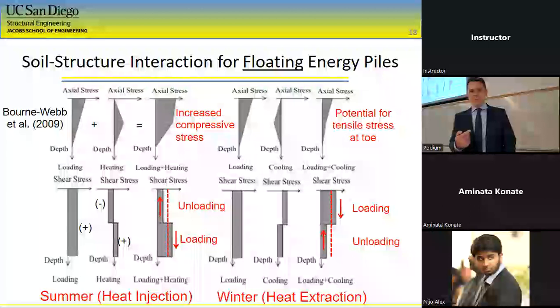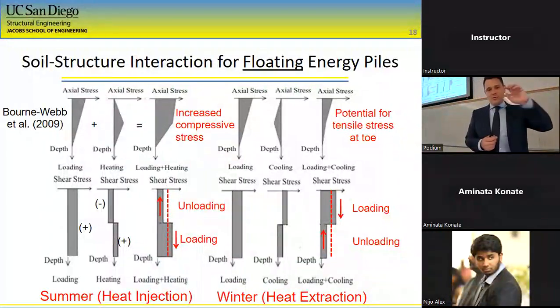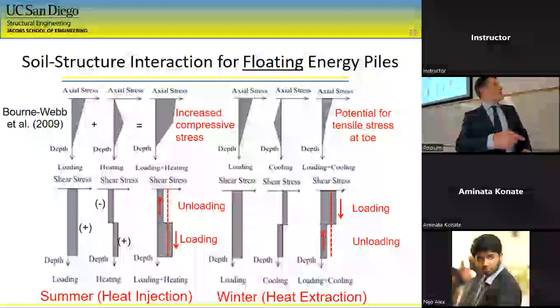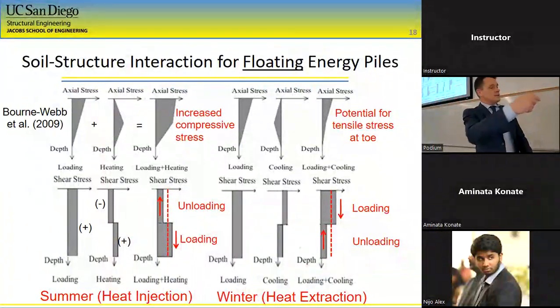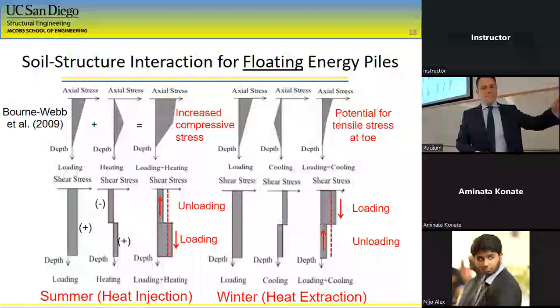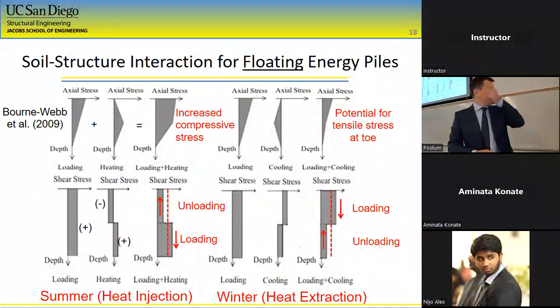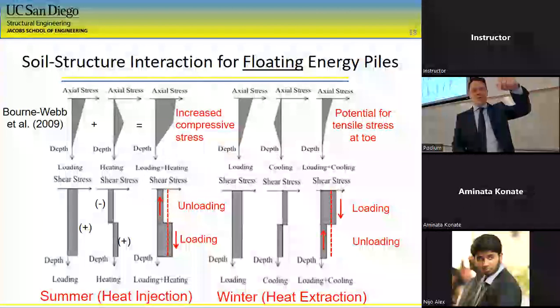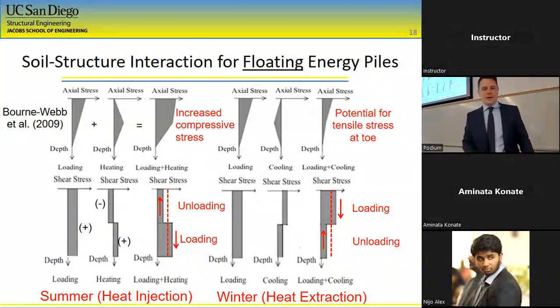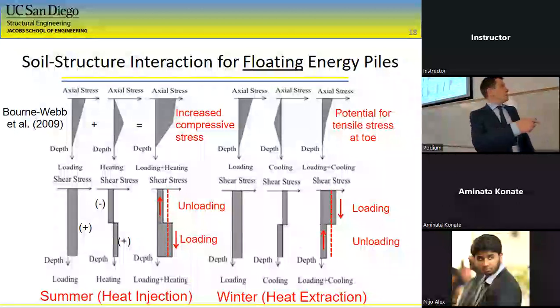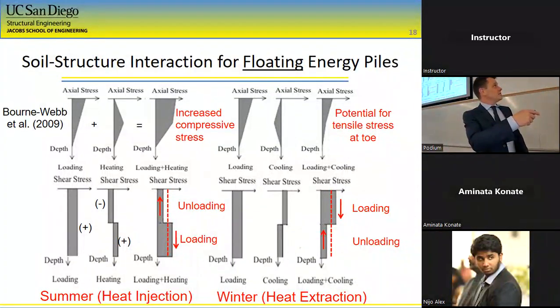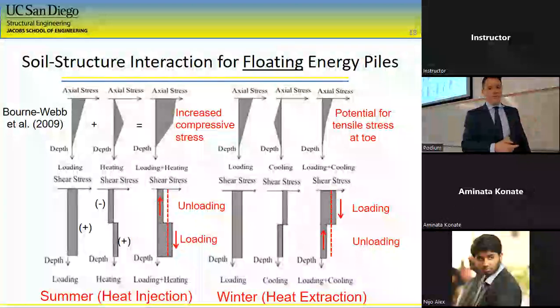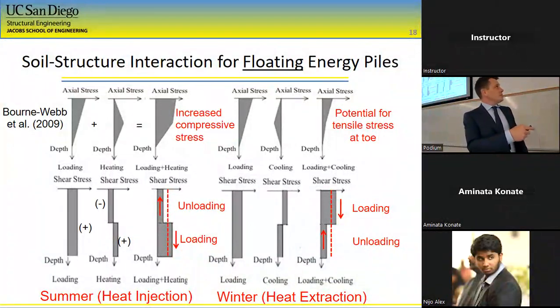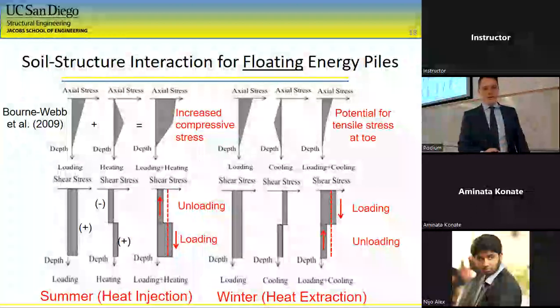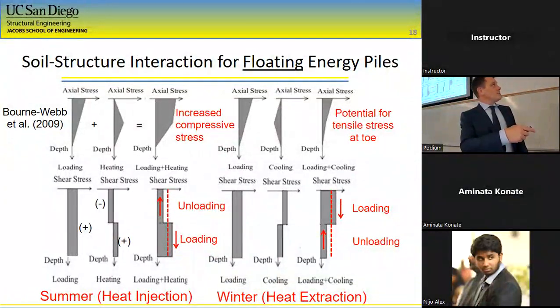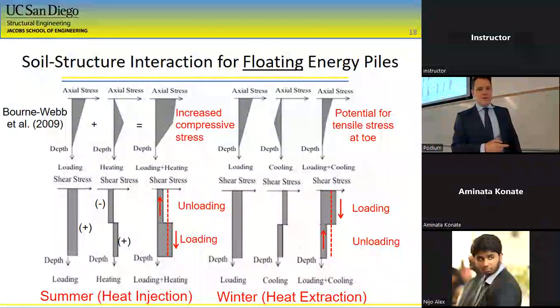So for a very simple case where you have a floating energy pile, this is a pile that has no end bearing. If you apply a load to the top of it, its stresses are going to be distributed somewhat linearly with depth. So at the bottom, there's no stress, and at the top, you're having a stress equivalent to the applied building stress. And then you're going to superimpose on top of that the stresses due to heating. So you add those together and you get an increased stress profile. So you need to make sure that these are within the capacity of the pile itself. And then when you cool it, you're having the opposite case. You could have tensile stresses at the toe.